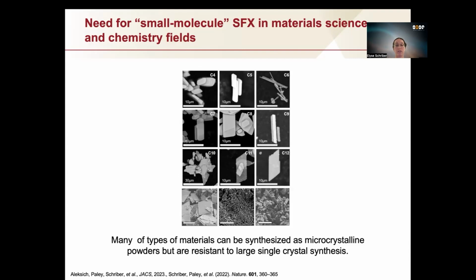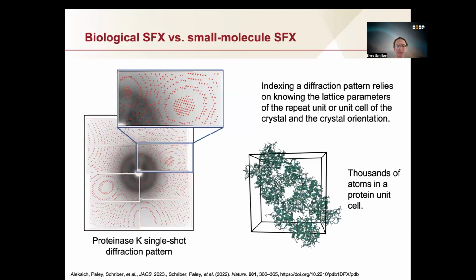Many types of materials, it turns out, can be synthesized as microcrystalline powders, but are resistant to large single crystal synthesis. And while synchrotrons can now be used to do things like serial crystallography, we still run into a problem where a synchrotron cannot quite produce the amount of flux needed to measure a crystal that's 5 to 10 microns in size. So there's a significant need for small molecule serial crystallography in the material science and chemistry fields.